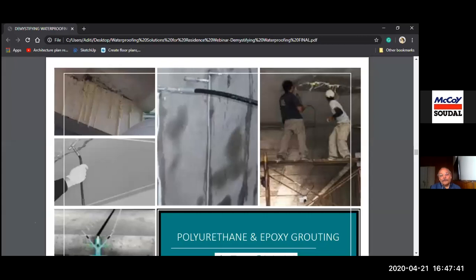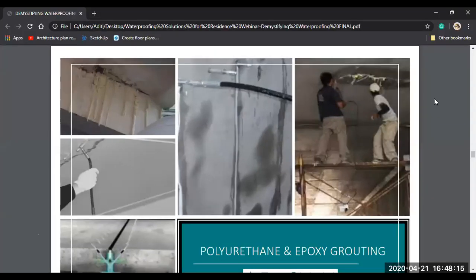PU grouts, single component or two components, are hydrophilic. They react with water, and there's a foam inside the wall. It stops water instantaneously. In places where the water ingress is very high, if you use a crystalline grout, which I discussed a while back, and after that use polyurethane, I have experience that the water stoppage is better than anything else. Of course, if you pour only polyurethane, nothing like it. But in larger sites, when there are big voids, the costing also has to be seen.